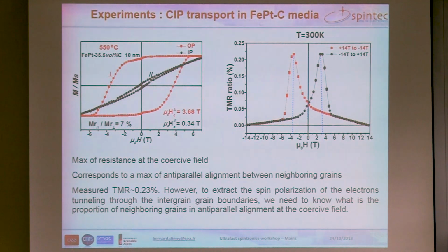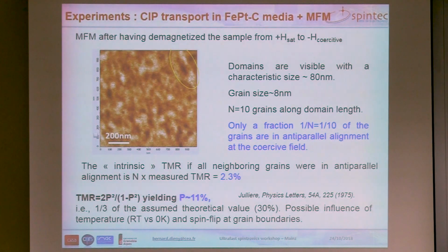But now this TMR amplitude is not very large. We measured 0.23%, but we are interested in knowing the intrinsic magnetoresistance of each junction. Here, this is a kind of effective magnetoresistance of the media, but if we want to access the magnetoresistance of each individual tunnel junction, we need to know the proportion of grains which are in parallel or antiparallel alignment at the coercive field.